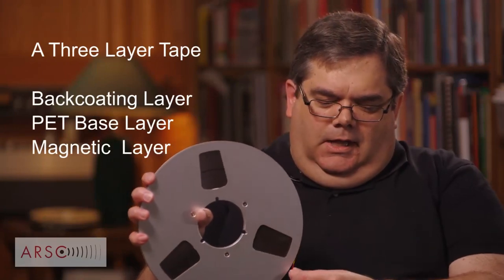The back coating and mag coating changed in this era. Chemical manufacturers were working with tape manufacturers to try to have more magnetic particle load and less glue in the coating while still being stable — and it seems they missed the mark a bit. It's a very complicated taxonomy of what tape does what, and it's really not going to be 100% knowable. Most of these formulations were trade secrets and are not published. Storage conditions also have a large impact on how your tape will behave today.